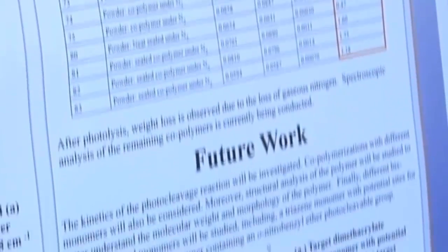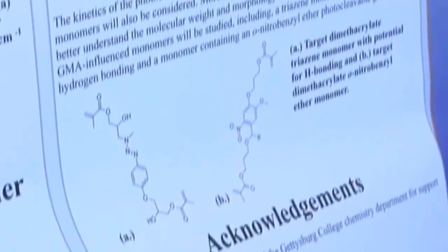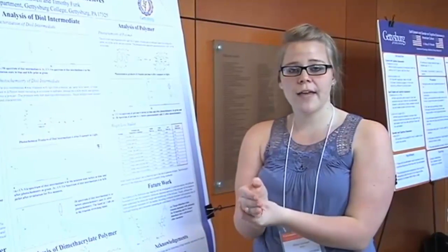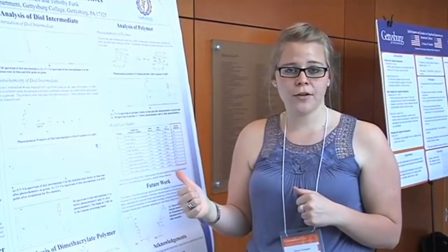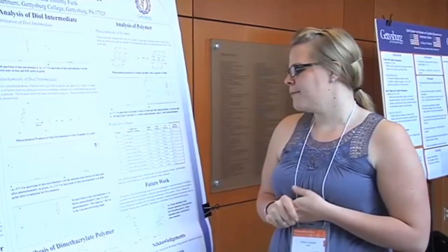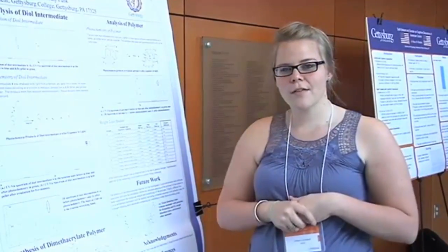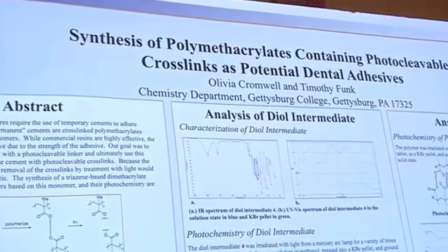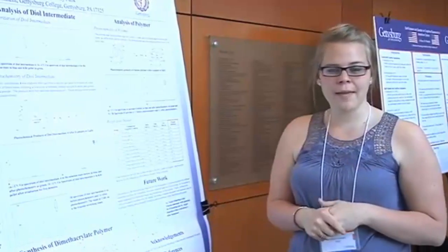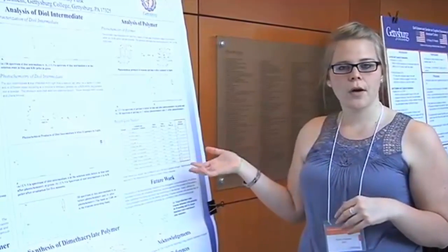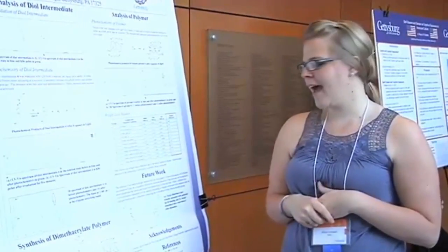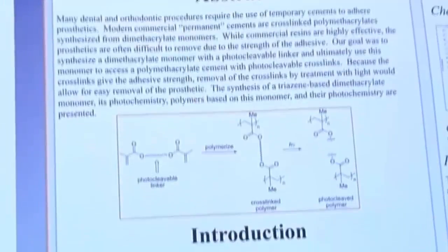The final thing that we looked at was what would happen because, upon irradiation of light, the triazine unit gives off molecular nitrogen. So we studied the weight loss due to the loss of nitrogen gas. And we did see that for the different polymers that we made, there was weight loss observed, and therefore we could determine that photocleavage had occurred.